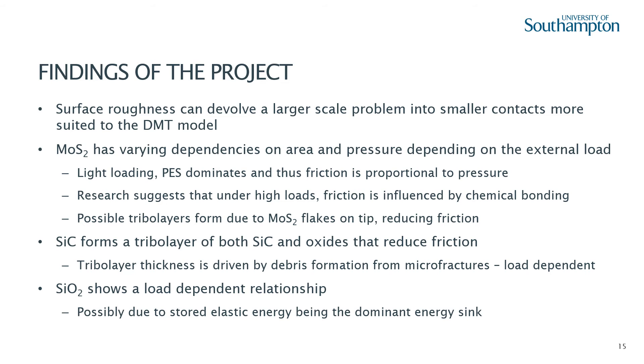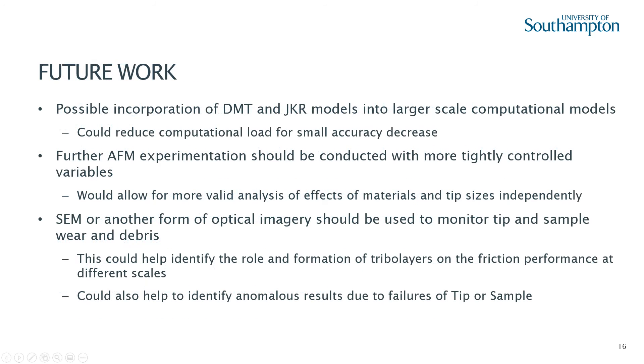Experimental results and conclusions were supported by previous research. Some of these included the dependence of MoS2 on both pressure and area due to its potential energy surface, and due to chemical bonds forming under higher loading and thus becoming the dominating friction force. Silicon carbide is known to sustain microfractures, the debris from which can form a tribofilm and reduce friction. The performance of this tribofilm can be influenced greatly by humidity and atmospheric conditions. Silicon dioxide showed the most simple linear relationship with load, decaying slightly as load increased — predicted by computational models suggesting elastic deformation is a large contributor to friction. Due to the simple nature of the models considered, they may present as a substitution to more complex finite element simulations in larger macro-scale computations, in order to speed up computational models at a small cost to accuracy.